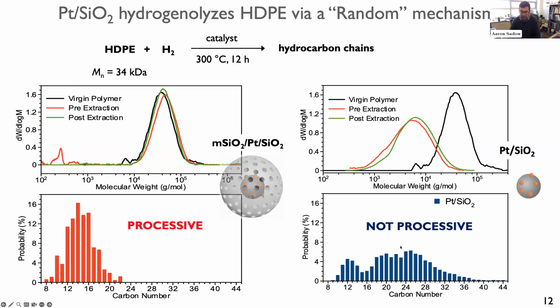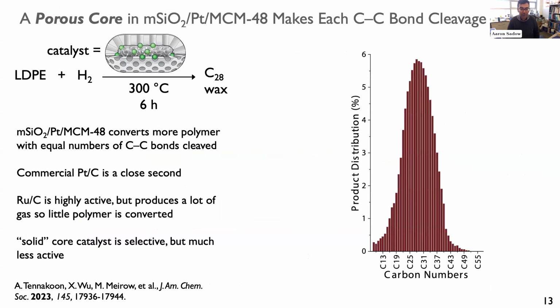And then the small molecule products are really this tail. So when we extract we get this broad distribution out, and that's really the tail of the average cleavage from random C-C bonds being broken as they're adsorbing down onto this platinum on silica catalyst. And this is kind of the general phenomenon that most catalysts give when you look at, say, hydrogenolysis of polyolefins. But I would say more generally, the random cleavage of polymer chains is going to give these distributions. So that doesn't allow for selectivity.